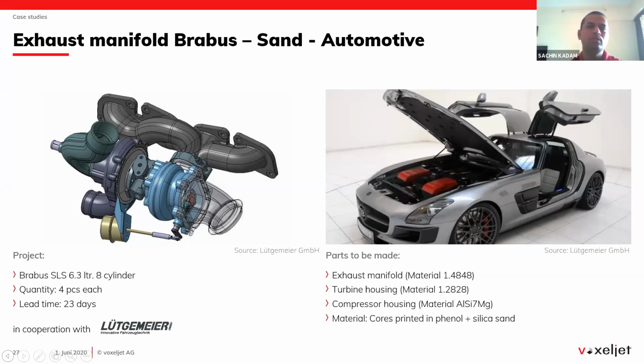These parts for this Brabus are produced with the phenolic binding technology. The phenolic binding technology is also a sand process, where normally in silica sand you use the furan binder, where the binding takes place at room temperature, but in phenolic you need to heat the job box at 100 degrees Celsius, and also there will be an IR lamp to heat the surface of the sand for the bonding of the material.